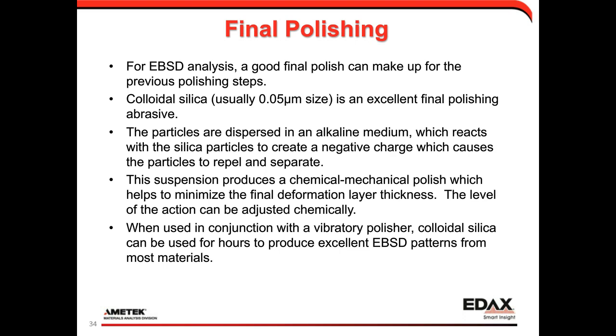In this case, the silica particles are in an alkaline medium. The important part of that is that it has a pH value that produces a chemical-mechanical polish. So as we polish, we also have a little bit of a chemical reaction that really helps minimize the final deformation layer thickness. It basically removes that little bit of deformation. It is possible to adjust this action chemically. Some people will add some chemicals to adjust that pH. Generally not something that I do, but you can see references to that in the literature. And when you use colloidal silica in conjunction with a vibratory polisher, you can use it for a few minutes to a few hours to produce really nice EBSD patterns for most materials.